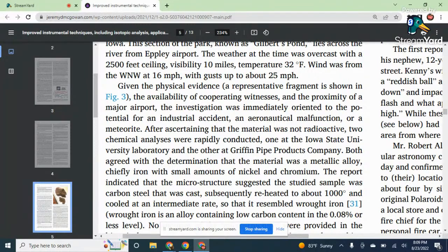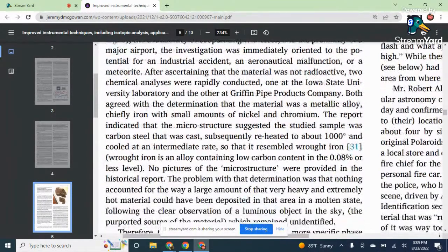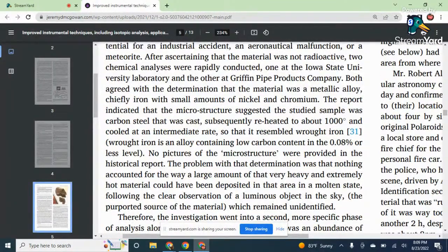After ascertaining that the material was not radioactive, so they tested it for radioactivity, very good, 2 chemical analyses were rapidly conducted, one at the Iowa State University laboratory and the other at Griffin Pipe Products Company, a private company. Both agreed with the determination that the material was a metallic alloy, or it was formed from more than one metal. It was a mixture, chiefly iron, with small amounts of nickel and chromium. So it was mainly iron, and there was a little bit of nickel and chromium, 2 other metals.